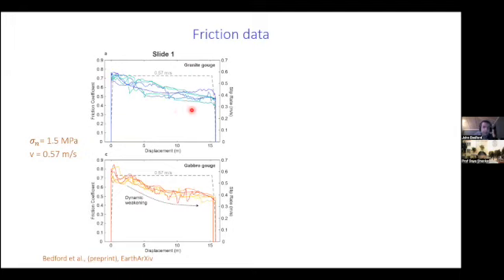which is actually not a very big dynamic reduction in frictional strength, but these are done at not super fast velocities compared to other studies, and also at quite low normal stress. So it's actually quite comparable to other studies at these conditions. But if you do it at high normal stress or at higher slip velocity, you would get more significant weakening. And then we held the layers. Each of these curves is a different experiment.